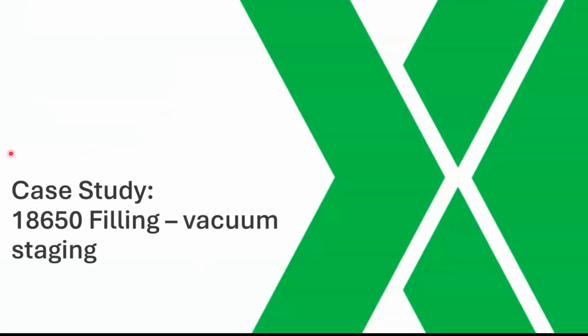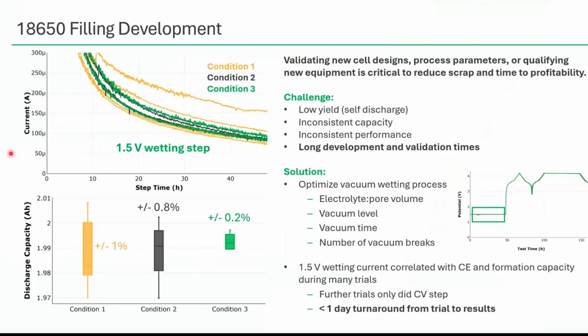Another quick case study, relevant again for cylindrical cells - though really it can apply to any cells. This was a study we did when trying to optimize filling and wetting conditions for a certain spec of 18650. When cells are in a very constrained environment, especially as we try to increase energy density and get to manufacturing, it's critical to validate these process steps and optimize how to get there faster and more consistently. This case study was about figuring out optimal conditions for vacuum staging during filling - we did multiple injections of electrolyte into 18650s, then different vacuum staging procedures before crimping and putting them on formation.